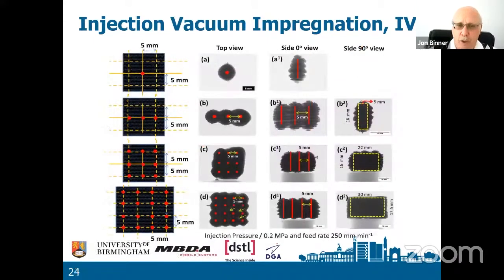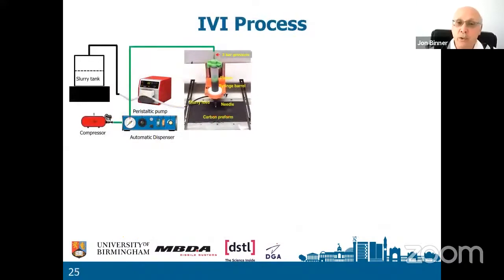We did a lot of work on working out, so these are taking the preforms, injecting them with 1 injection, 3 injections, 9 injections, and more, and then using micro CT to work out how much the slurry spread. Since we did this work, we've had an entire PhD on this to really understand the process and the science behind the process. We can use an automated system. So the injection was initially done by the student or the researcher injecting, and they ended up with a thumb that was really quite tired by the time they'd finished injecting a large plate. So we moved the whole thing onto an automated system.